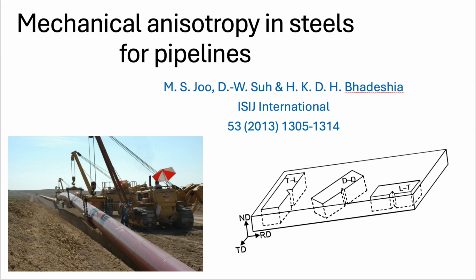Chemical segregation causing banding. That's it. Microstructural banding. It goes back to how the steel first solidifies from liquid. As it cools, some elements, manganese is a key one, but also silicon and phosphorus, tend to get pushed into the liquid that solidifies last. These are the interdendritic regions. So even in the solid slab, you have tiny variations in chemistry. Some spots are richer in certain elements than others.